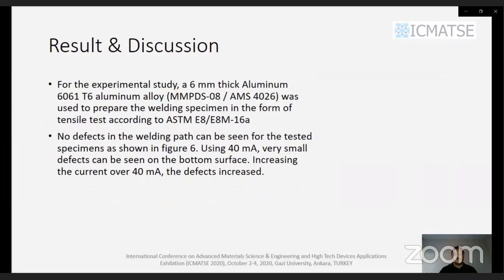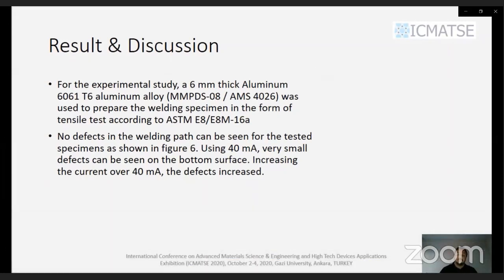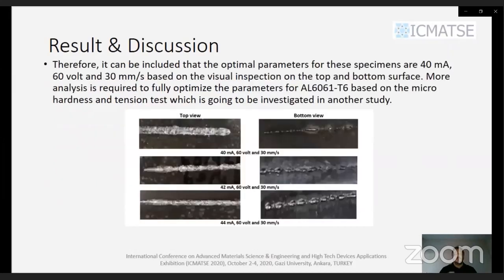So, for the experimental study, a 6 mm thick aluminum 6061 T6 condition aluminum alloy was used to prepare the welding specimen in the form of a tensile test according to ASTM E8/E8M 16A. No defects in the welding path can be seen for the tested specimen as shown in figure 6. Using 40 milliampere, very small defects can be seen on the bottom surface. Increasing the current over 40 milliampere, the defects also increase. So here you can see the results of the experimental values.